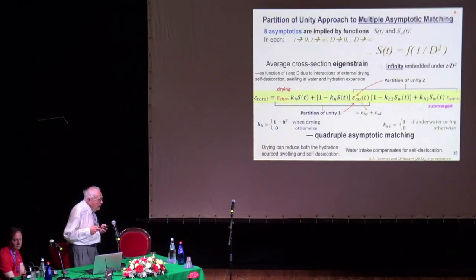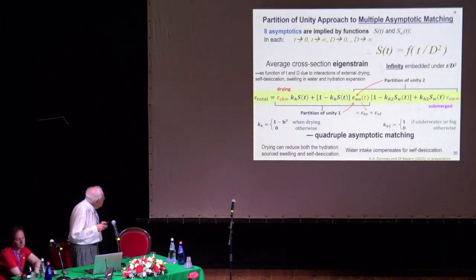This is it. Now, combining it, we are trying now to do it by this formula. Total deformation is combined shrinkage. This is the asymptotic value due to drying. This is the autogenous shrinkage, a function of time, and the asymptotic value of swelling due to expansion. It must all be expressed in terms of this dimensionless variable. You have here these asymptotic conditions, which are actually eight of them.